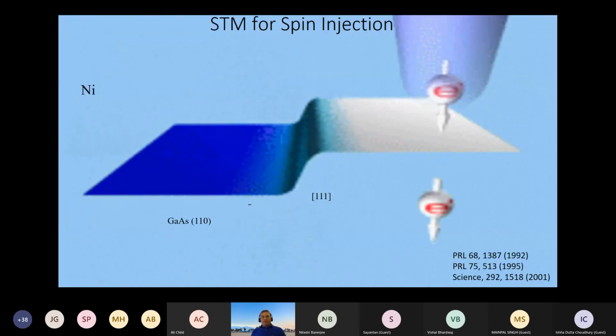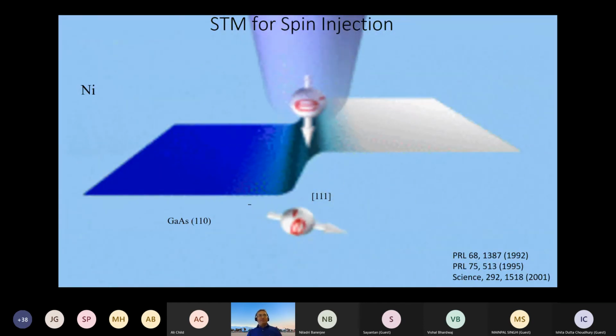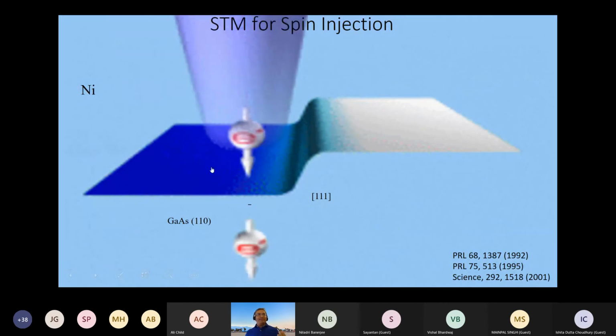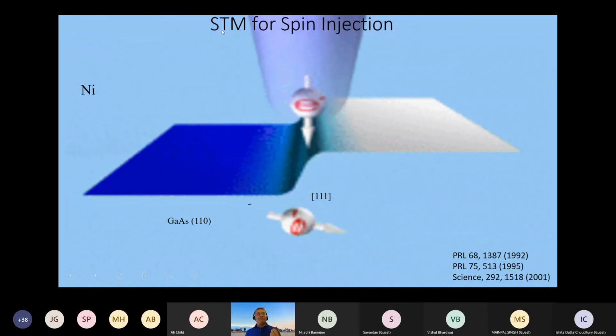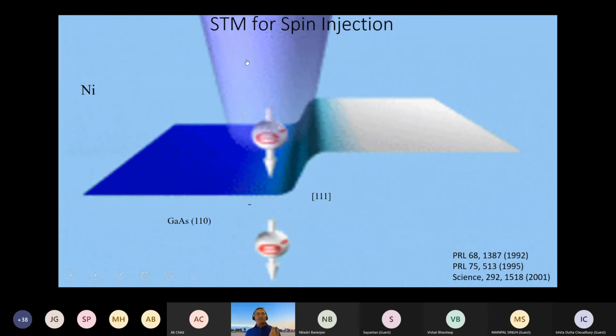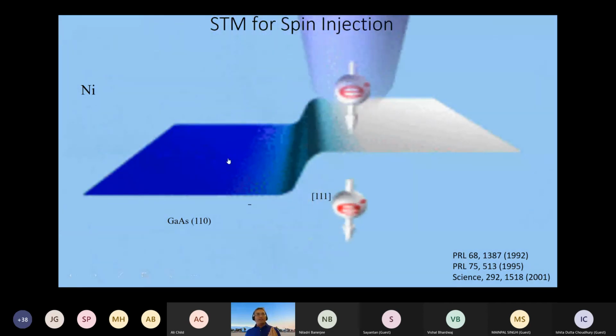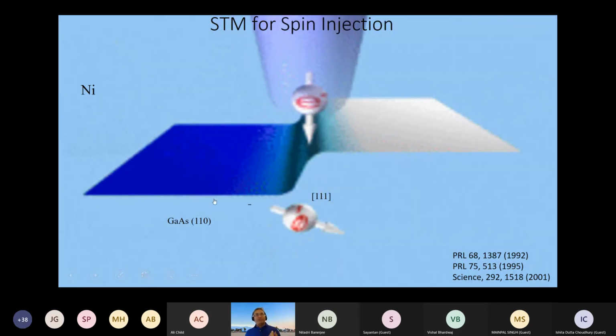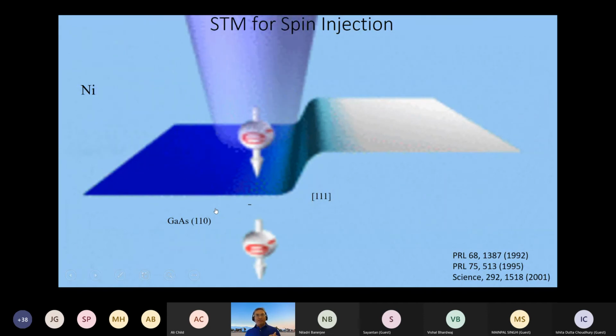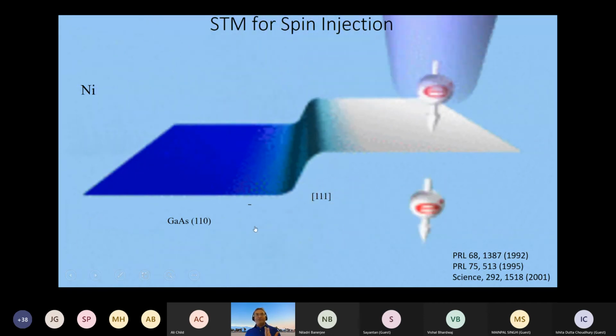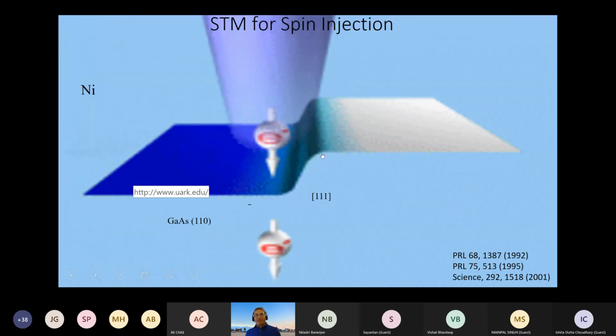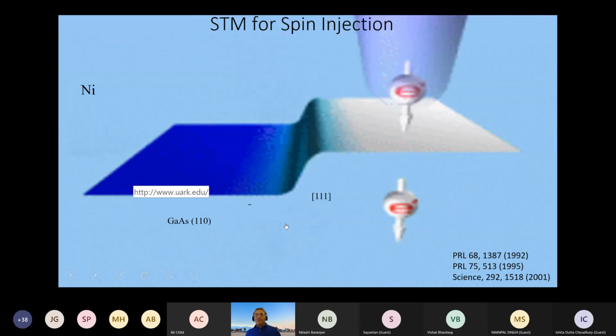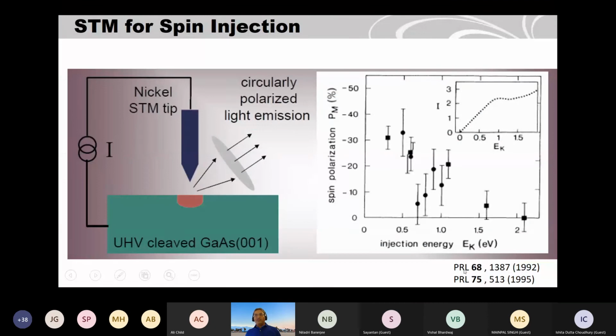And also, it was interesting to see that people could inject spins from a ferromagnetic STM tip, a scanning tunneling microscope tip, but it's a ferromagnet, and this is gallium arsenide. So they could inject the spin into gallium arsenide. And here is a cartoon just showing how spins are injected, and it can be flipped when you have a step-like feature here. But the real papers are here.